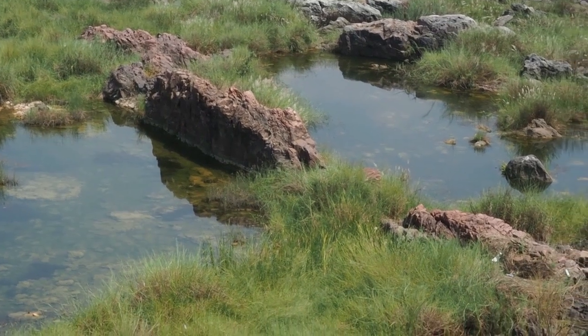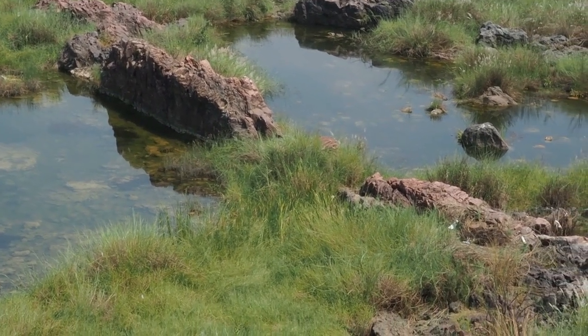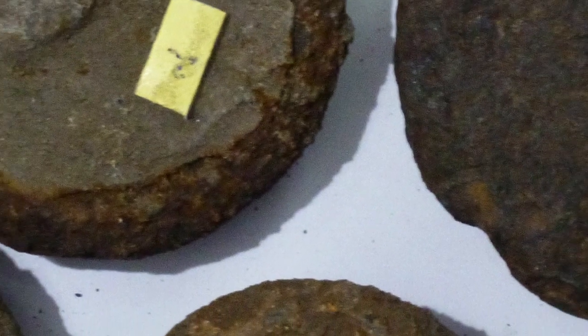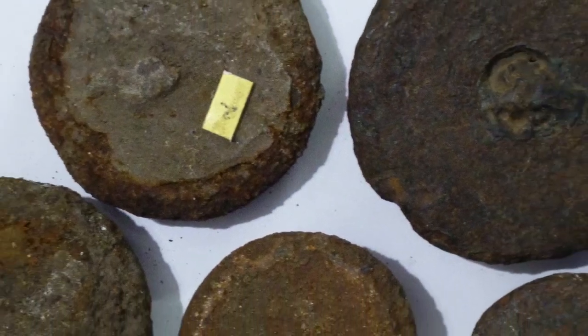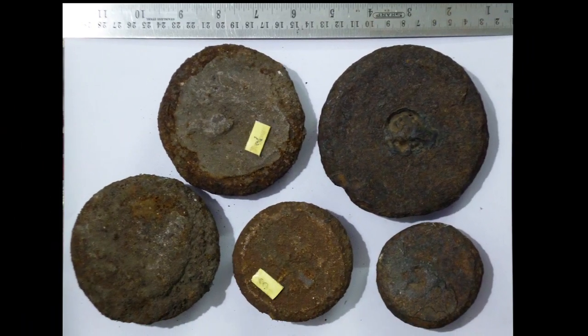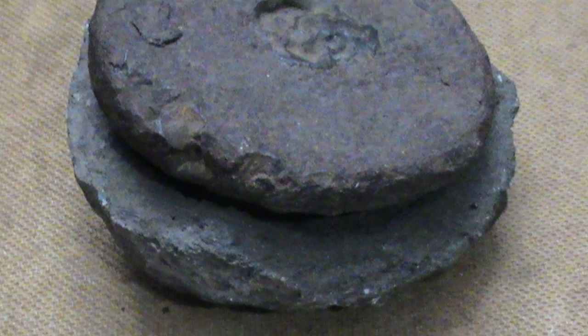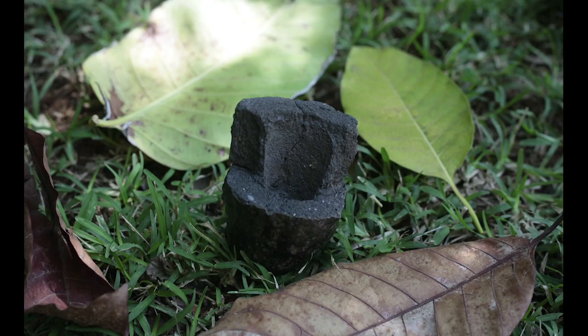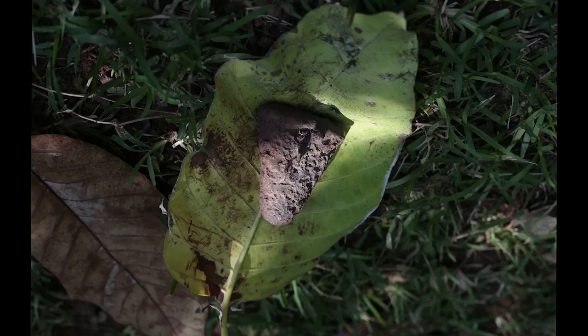The smelted iron blooms were often used as raw material to make the famed high-grade wootz steel or ukku, the word for steel in local languages recorded by travellers such as Voysey in the 1800s. Tens of thousands of ingots of wootz steel were shipped out of the Golconda region, according to the 17th century traveller Tavernier. Whereas bloomery iron has a low carbon content of less than 0.04%, wootz steel is basically steel of a high carbon content of around 1.5% carbon.